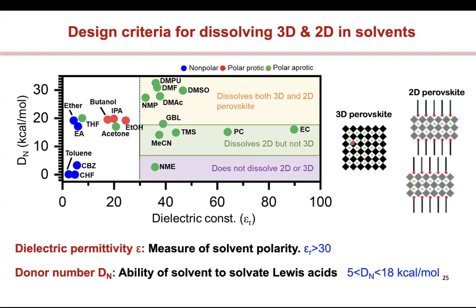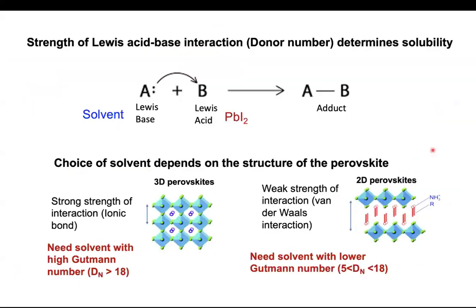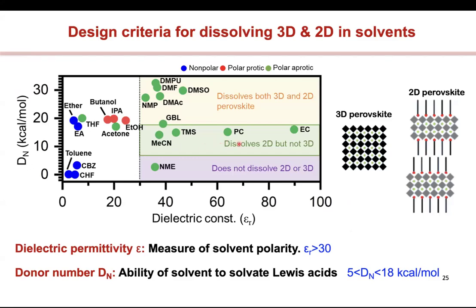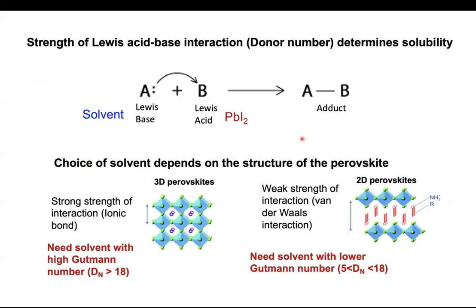And these are the two structures, 3D and 2D typically. And so we wanted to do that. And so we wanted to understand what makes it really dissolve a 2D but not a 3D perovskite. Okay. And so if you look at these basic interactions, right? So what I'm showing you is the strength of these Lewis acid-base interactions, which you may have done. This determines solubility.